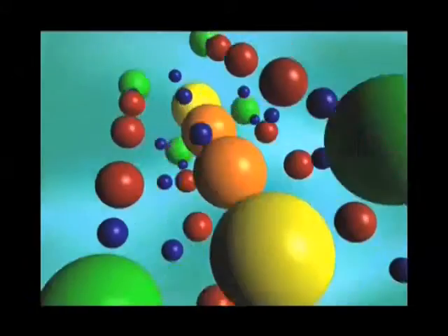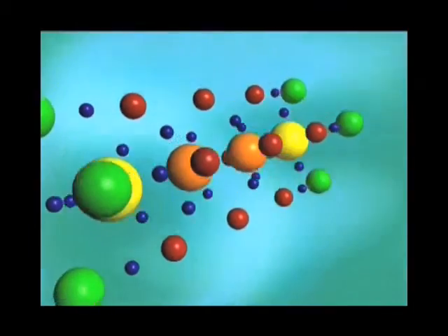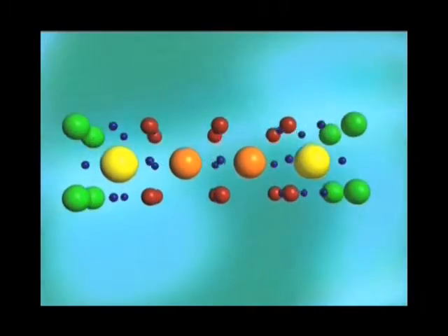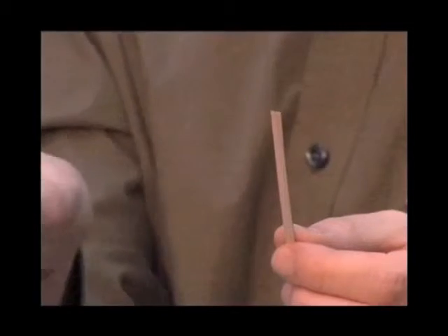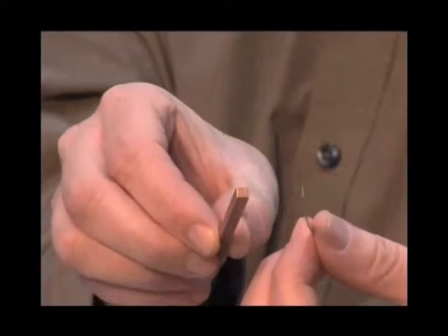with conventional non-superconducting materials. Tapes are made out of the brittle ceramic material in an elaborate high-tech process. In the superconducting state, these tapes are capable of carrying 30 times more current density than copper. This superconductor can be operated with a current of 100 amperes. For comparison, a copper conductor would need this cross-section.